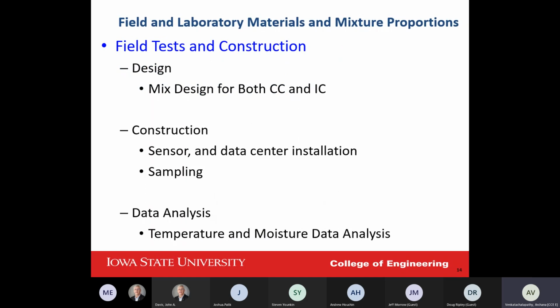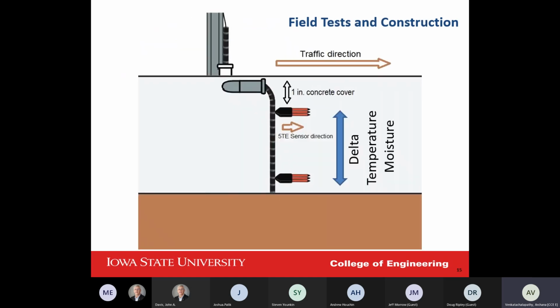Anyway, those are just lab results, but in the field we also put in sensors for measuring the temperature and moisture in the concrete slabs. We placed them 1 inch from the surface and also 1 inch from the bottom, so we could compare the top and bottom temperature and moisture of the concrete.